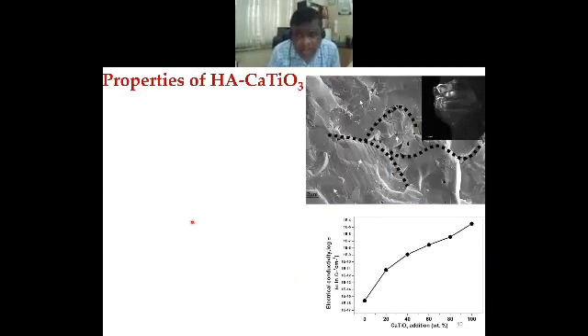Now, what is the origin of this fracture toughness enhancement? We have seen in transmission electron microscopy a twinned microstructure in the calcium titanate phase. Similar observations we have also seen in the fracture surface. You can see several twins clearly observed on these calcium titanate grains, and that leads to a lot of crack tortuosity in the materials. In terms of electrical conductivity enhancement, with the addition of 40%, we are getting close to 10 to the minus 8 ohm inverse centimeter inverse, and that is a reasonable conductivity in the material surface.